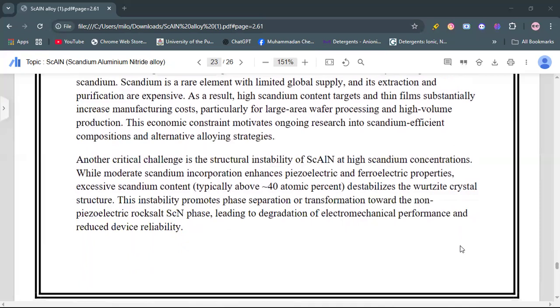Another critical challenge is the structural instability of scandium aluminum nitride at high scandium concentration. While moderate scandium incorporation enhances piezoelectric and ferroelectric properties, excessive scandium content, typically above 40 atomic percent, destabilizes the structure. This instability promotes phase separation, leading to degradation of electromechanical performance and reduced device reliability.